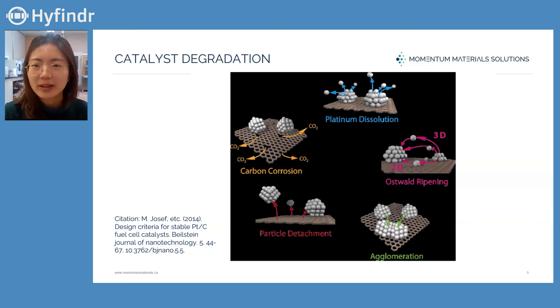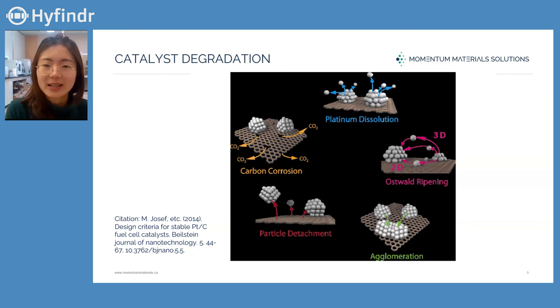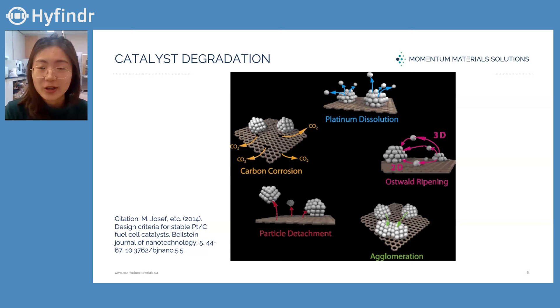Is it really true that nothing happens to the support material during the reaction? Doesn't it all heat up, and doesn't it wear and tear over time? That's a great question. Even though we hope the support material — and the platinum — to not be consumed or changed during reactions, such reactions did happen during operation. This slide shows some of the typical degradation reactions happening during system operation. Platinum as a catalyst could be degraded due to detachment from the support material or dissolution. It could also lose its electrochemical surface area due to ripening or agglomeration. Carbon material, even though it's quite stable, still experiences corrosion reactions during operation.